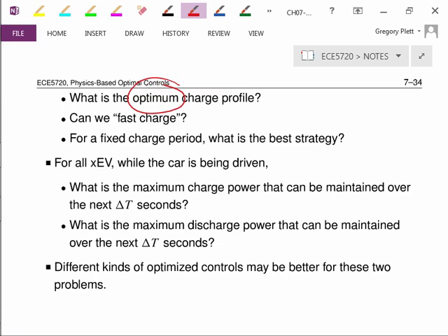And the two mechanisms that we looked at, the SEI growth and the lithium plating, are worst when we're charging. If I'm not charging, lithium plating can't happen. And if I'm not charging, the SEI layer growth is going to be extremely slow, just kind of resting. But if I'm charging, both of those are going to be accelerated. And so how do I consider that in my charging strategy? Do I want to charge really slowly, or do I want to charge quickly? How should I charge it? So we're going to look at that starting in the next section.